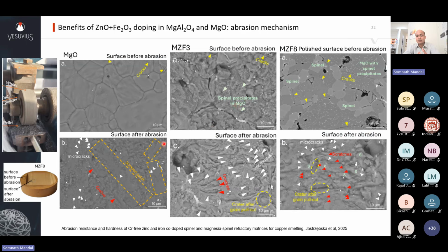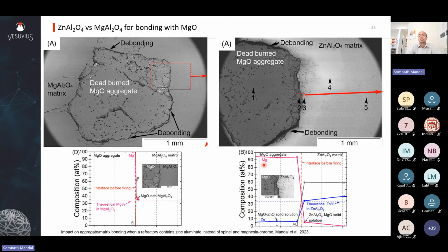If you look a little closer, what you see after these abrasion tests with silicon carbide grit is that in magnesia, you have big scraped patches of missing material and this uniform abrasion of the material. Whereas in the zinc and iron doped, you see a lot of these spinel precipitates, and it gives you some sort of precipitation hardening effect. And these precipitates help to improve the abrasion resistance. You don't have these smooth patches, you have more grooves and micro cracks. These are indications that it is really resisting the passage of silicon carbide grit particles on its surface. So this gives rise to the abrasion resistance.